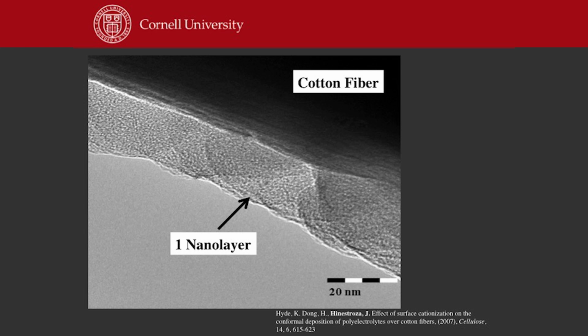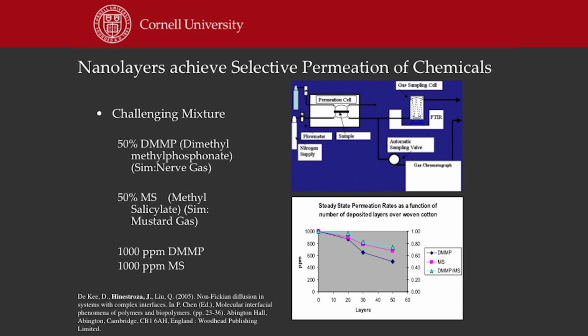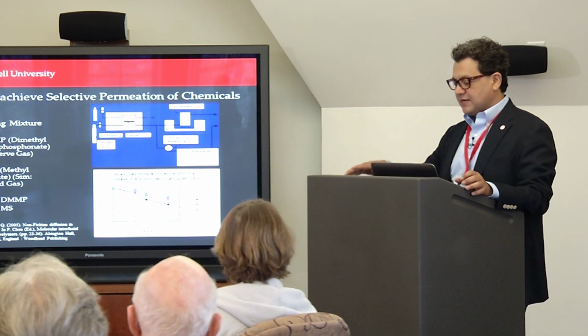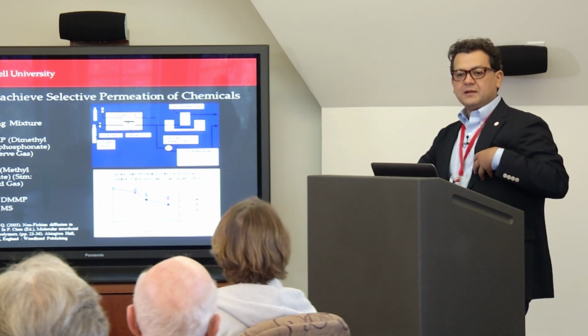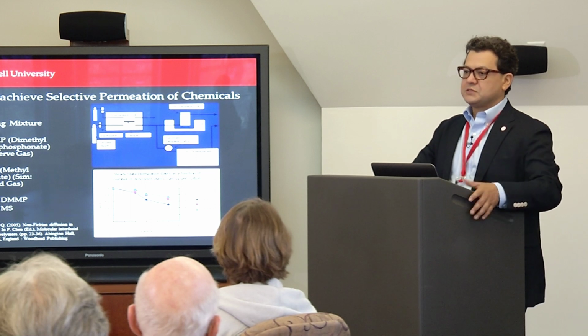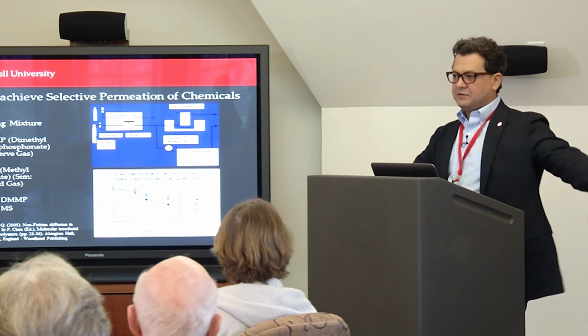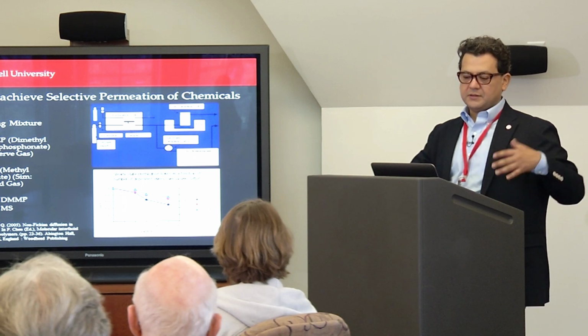And then we actually tested these materials against different gases, in this case, nerve gas and mustard gas. And we were able to prove how we can control the gases, how they move through the interfaces with these little layers of only 20 nanometers. So you are not changing the properties of the cotton. It's the same cotton. You are just adding this very small amount of polymers. Now, not only nerve gas and mustard gas, but you can also control how the humidity from your body gets out or doesn't get out. Some sports, you want all the humidity to get out really fast, and some sports you need a layer of water, yeah? So now we can control at what speed they move.